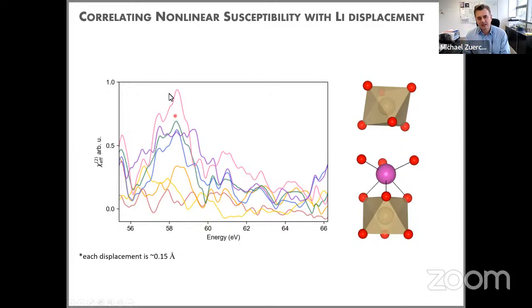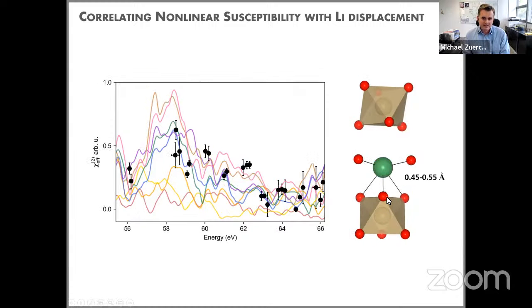So that gave us confidence that we can actually measure this and use the relative strength of the second harmonic as a sort of quantifying of this displacement of the lithium atoms. Okay, and so now this is the data that we measured on top of that. You can see, well, it's noisy, so these measurements are challenging. The photon flux overall is not very high, and you have to collect lots of shots and then correlate them.